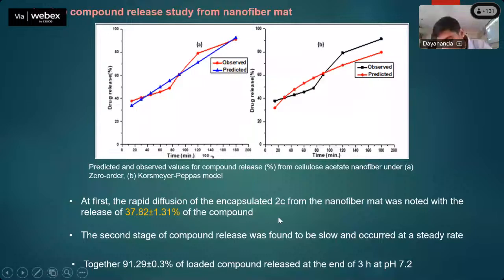In the beginning, one could find rapid release of 37%, and after that, in the second stage, there was a slow and steady release. So altogether, 91% of the loaded drug was released in 3 hours at pH 7.2.